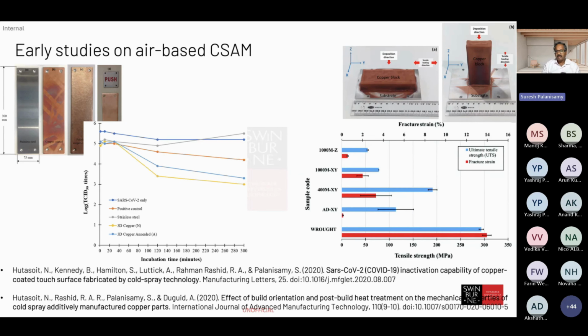Not all materials might be possible. However, some of the highly reflective materials like copper, when you have a laser-based system to print, copper is quite reflective, and aluminum is also quite reflective. Some of the materials like that cannot be printed with normal technology but can be used in cold spray, because it's solid state. You're not melting the particle. That's one of the reasons. However, achieving the right properties is still a challenge. I'll show you how the property variations look. Most probably you can achieve properties similar to casting properties.